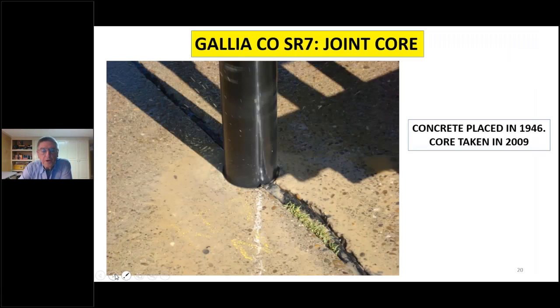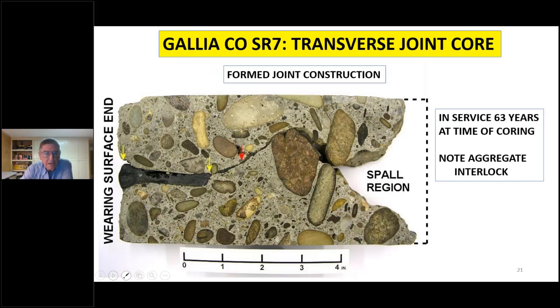This shows the coring, and you can see the material is still elastomeric at that time, after 63 years. The core was taken and looked at. We sectioned it and lapped it, of course. And this is that core from that transverse joint. And what you see here is that this is the form joint that is filled. It's still bonded to the sides.